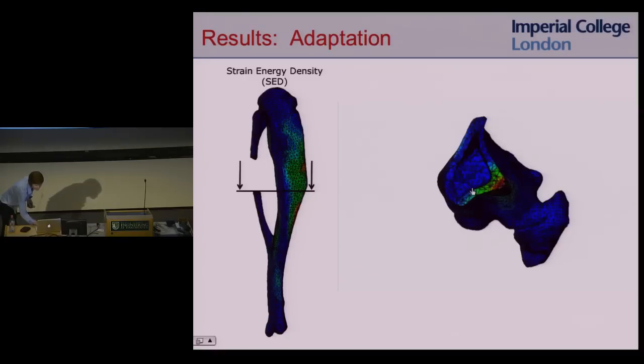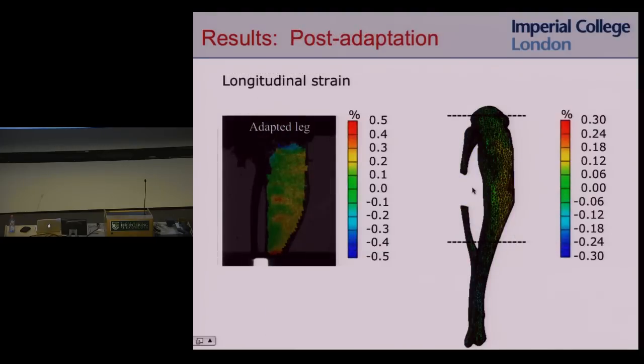So if we actually grow it, you can see the stimulus decreases and the bone gets thicker right there. So we're growing the bone in response to the stimulus. Not surprisingly, the stimulus goes down. So how do we do at the ends? Once we've got our homeostatic bone shape, how do the strains compare to the experimental strains? So here we're comparing the adapted bone that's gone through our algorithm and we've actually grown it and adapted it to what we measure on the adapted leg. And you can see, not very clearly because it comes fairly dark, but the strains are much lower and in the same ballpark as those experimental strains. So we're growing the bone in our adaptation, and the final adaptation we get matches what we see experimentally.